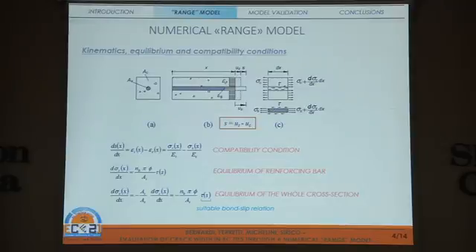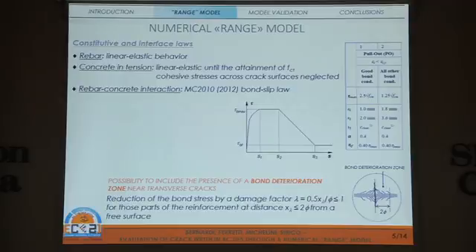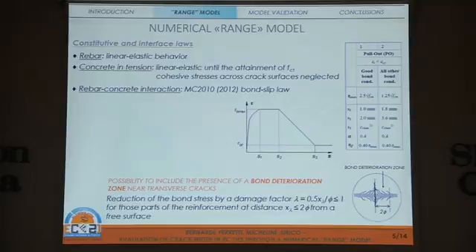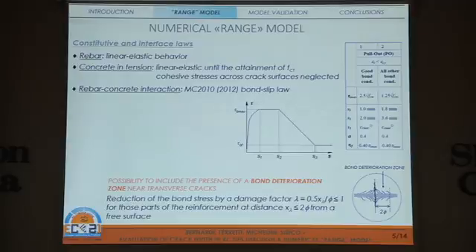The model assumes that the problem is governed by three classic differential equations of bond: the compatibility condition, equilibrium of the reinforcing bar, and equilibrium of the whole cross section. As regards constitutive laws, the rebar is assumed to have linear elastic behaviour since the problem concerns serviceability verification. Concrete in tension is also assumed linear elastic until attainment of the tensile strength, and after crack formation, cohesive stresses across crack surfaces are neglected for simplicity. The interaction between rebar and concrete is modelled by means of the Model Code 2010 bond-slip law.